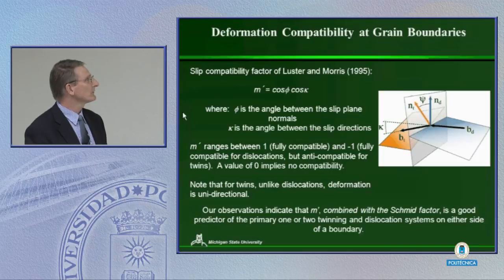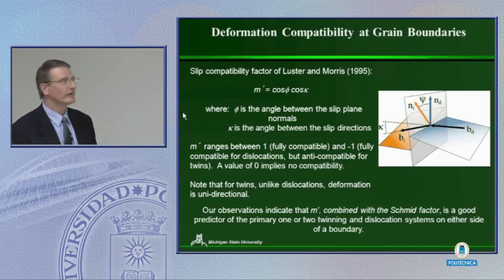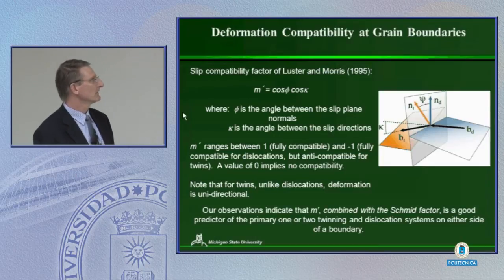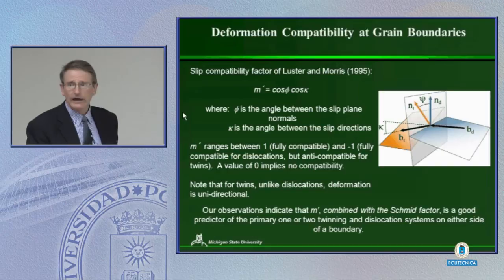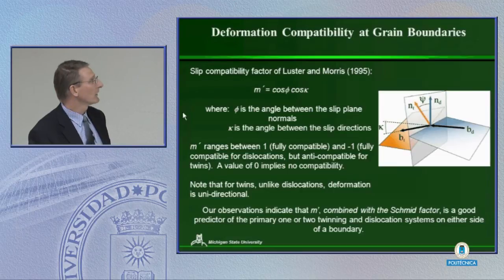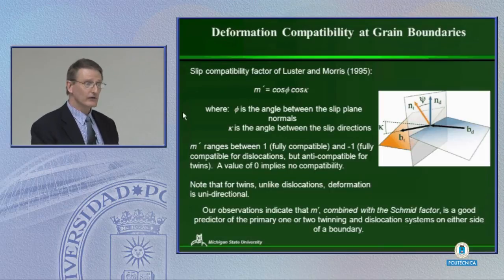And at first we looked at this in terms of a slip compatibility factor that was developed by Luster and Morris a number of years ago in titanium aluminum, which really just says how well aligned are the deformation systems. What is the angle between the slip plane normals, and what is the angle between the slip directions? And it would make sense that if those are well aligned, slip transfer might be easy and you won't get deformation. And so this factor here can range between 1, which says it's fully compatible, and -1, which would be fully compatible for dislocations, but it would be anti-compatible for twinning, because twins are unidirectional and you can't shear them in either direction. Okay? A value of 0 basically says that the deformation systems are at 90 degrees to each other.